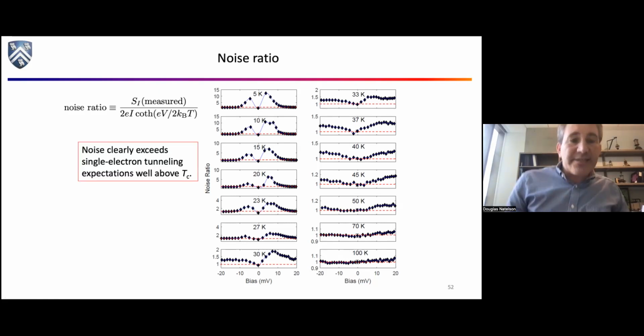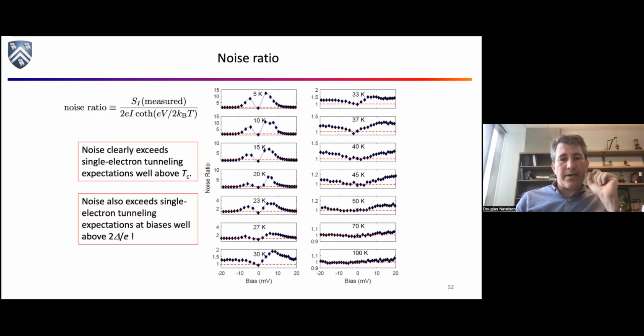So the noise clearly exceeds the single electron case. What does that mean? Well, it means that sometimes more than one electron is going through at a time. The more surprising thing, in some sense, is that this is happening at pretty high energies compared to the energy scale for superconductivity. That was a surprise to us. We did not expect that.